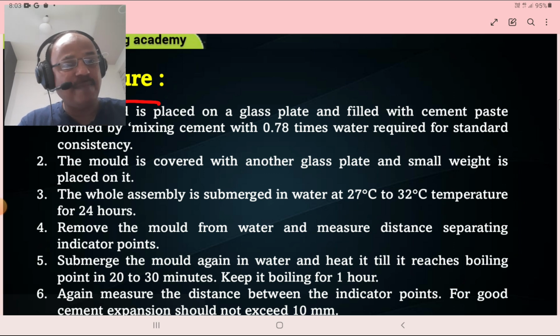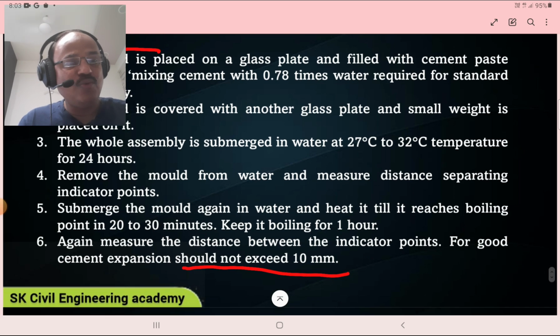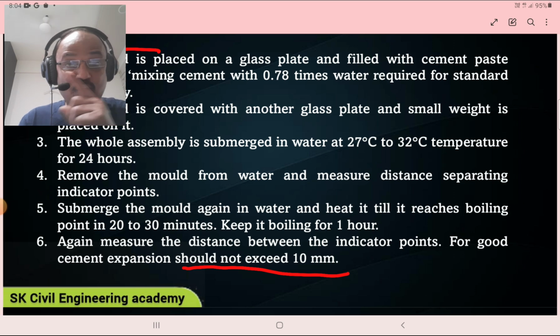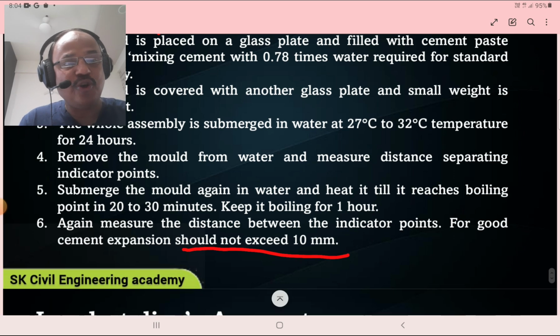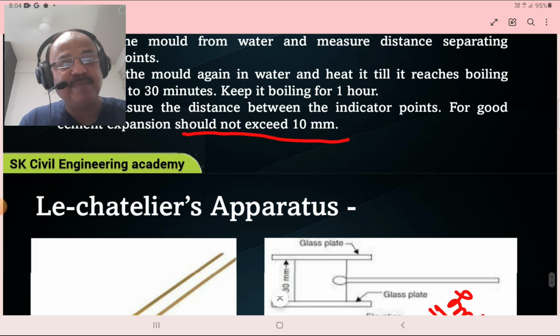The whole assembly is submerged into water at 27 to 32 degrees Celsius temperature for 24 hours. Remove the mold from the water and measure the distance separating the indicator points. Submerge the mold again in water and heat it till it reaches the boiling point in 20 to 30 minutes. Keep it boiling for 1 hour. That is important. 1 hour. Again measure the distance between the indicator points. For good cement, expansion should not exceed 10 mm.